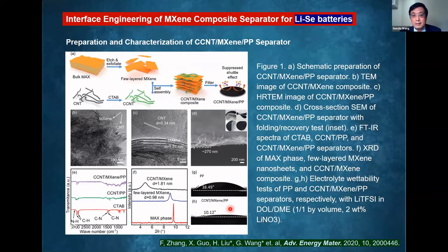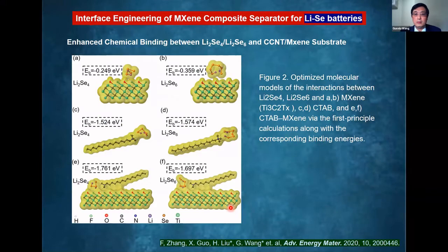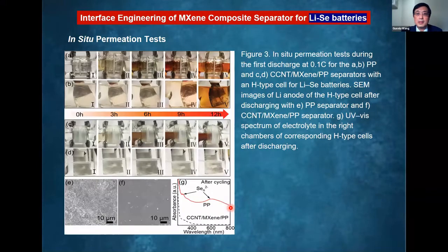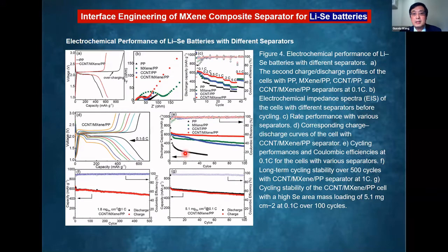That means it can improve the soaking property of the electrolyte on the separator. So also we did a DFT calculation, and particularly we did an in situ permeation test. You can see when we use MXene coated separator, we found it can effectively prevent the permeation of lithium selenide. And then we tested this MXene coated separator. We found this MXene modified separator can achieve much better electrochemical performance than when using the unmodified separator.